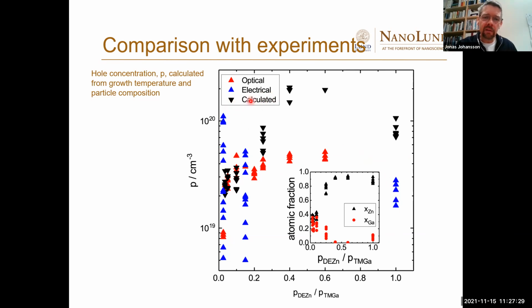So the calculated values agree quite well with the experiments, at least at the lower diethyl zinc concentrations, and maybe at the maximum, but here we have a stronger deviation. But still, it is very difficult to accurately calculate doping levels without any fitting parameters. So I'm quite satisfied with this anyway. So I think it's reasonable.